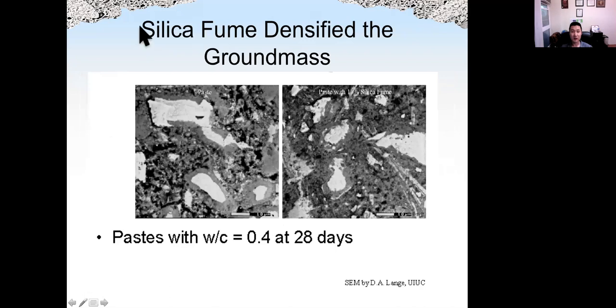So here shows silica fume densify the groundmass, which is one type of CSH, the hydration product. The picture on the left shows the paste with water cement ratio of 0.4. We see a lot of black, so that is voids. But with 10% silica fume, the same water cement ratio, we see much denser matrix, because we see much less voids, which is the black color.